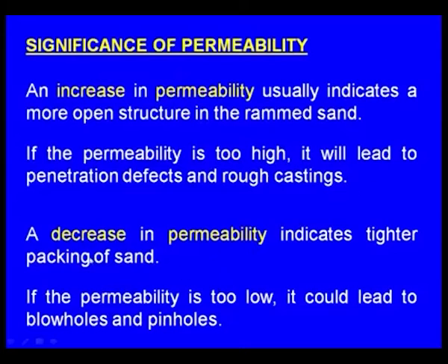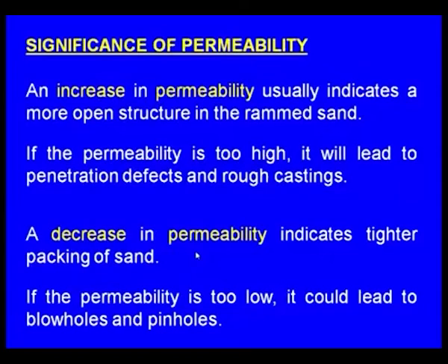Next one, a decrease in permeability. Now, let us see what happens if the permeability is too low, which indicates tighter packing of sand. Naturally, when we pack the sand very tightly, what happens? The clearance between the neighboring sand grains will be very minimum. In such a case, the hot gases may not be able to pass through the neighboring grains, so there is a decrease in the permeability. If the permeability is too low, it could lead to blowholes and pinhole defects.